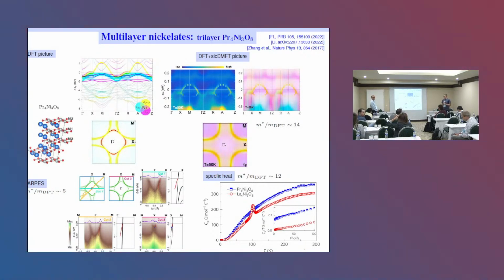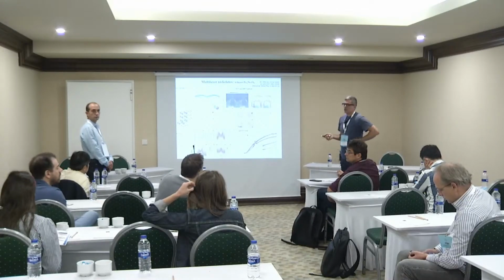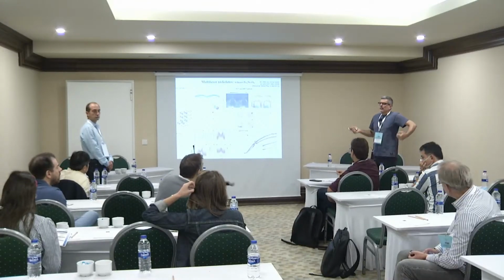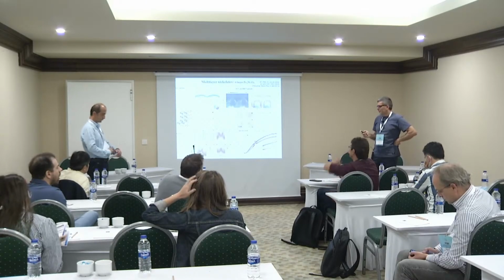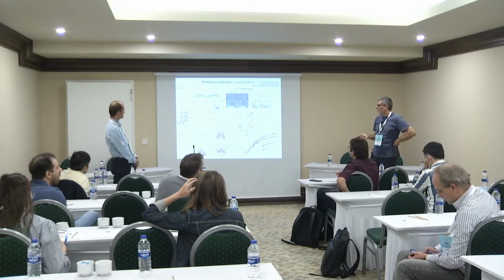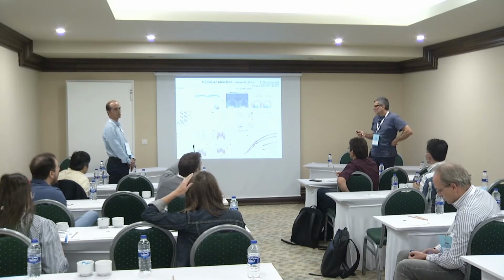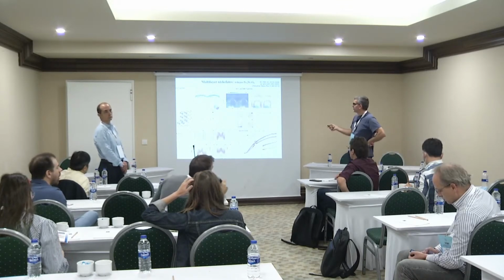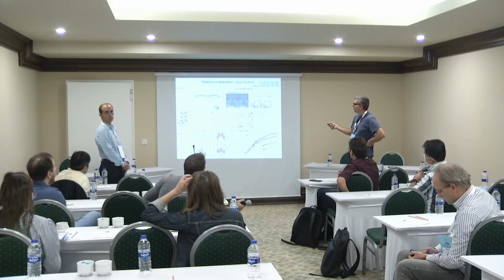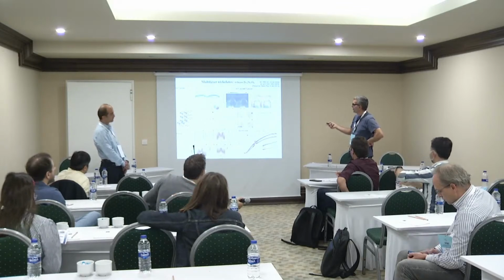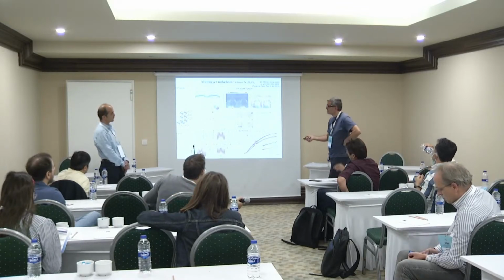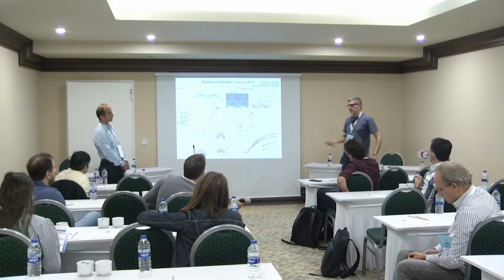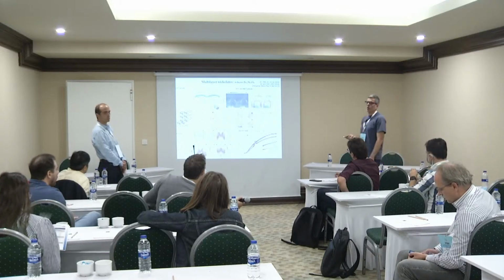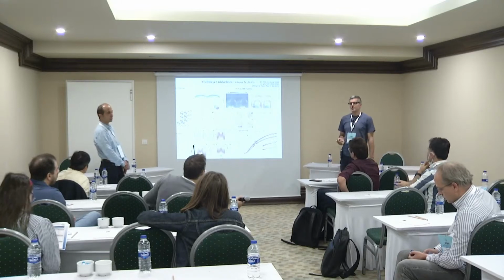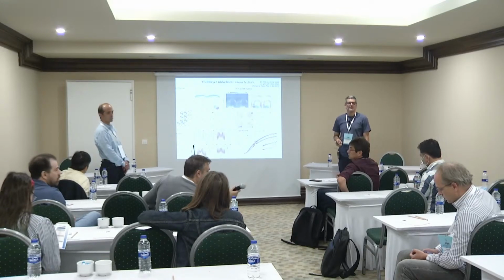Typically this kind of discrepancy between specific heat and ARPES means multi-orbital. Typically specific heat is very sensitive to what happens exactly at the Fermi level, whereas in ARPES we have this mixing in of the nickel d3z2-r2, although this whole flat band is above, but we have a mixing of the nickel d3z2-r2. So they don't see this in ARPES. I talked with Dan Dessau for a long time, but it's ongoing work, so to say. I don't want to judge experimental measurements.